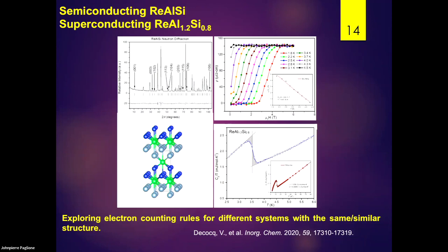Okay, because if we are getting the exactly 1:1:1 ratio, that's a semiconductor. So the Fermi level is in the semiconductor gap. So then we were thinking, can we move the Fermi level up or down, so that we will have electrons there? And usually the peak shape is very sharp, and between the two gaps there is a flat band. So what we think is, can we push down to the flat band? And then we see, because who knows what will happen. Maybe it's not superconductivity, maybe it's charge density wave. But I want to hit the flat band. So that's my logic. So we need to go to the flat band? Yes. So the electrons go to the flat band.